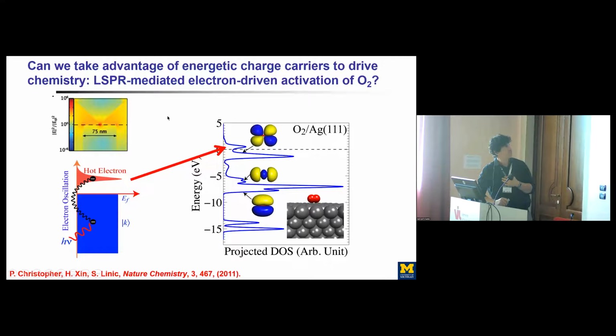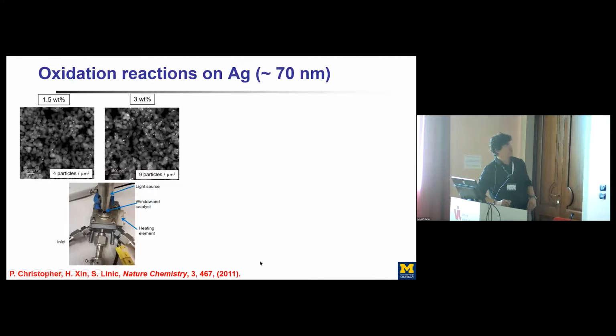So the concept here would be that you have an electron that's formed in this system, and then somehow this electron finds its way through this anti-bonding orbital, and in that process it dissociates this molecular oxygen, forming atomic oxygen, and then you can use that atomic oxygen, for example, to drive oxidation reactions. So this is the first experiment that we performed. We deposited silver nanoparticles, a very small concentration of silver, on an alumina support, and we designed a reactor that looks like this.